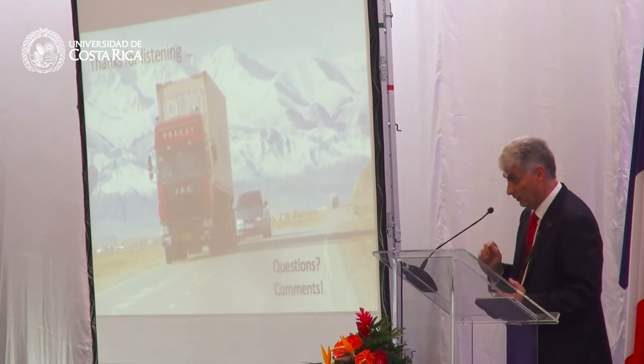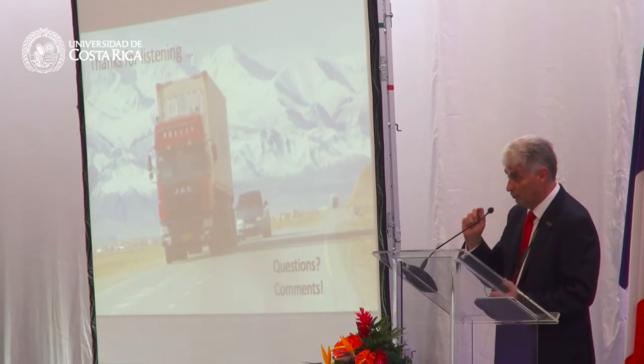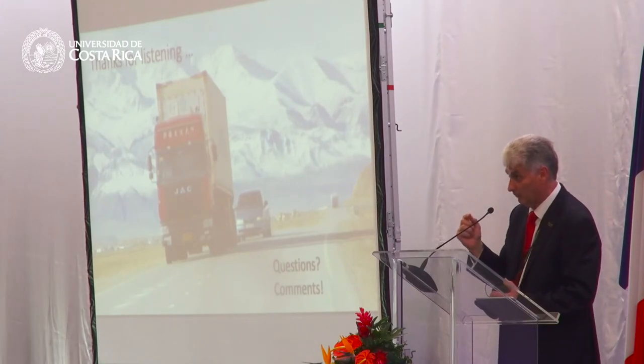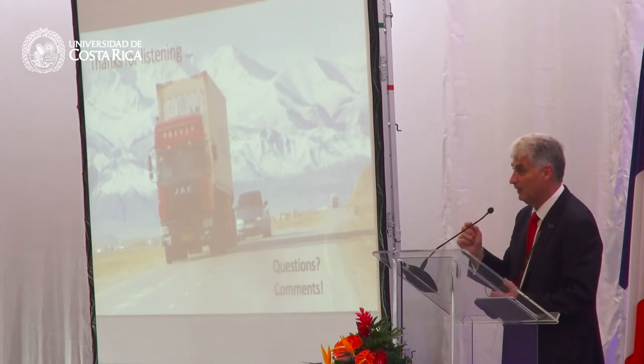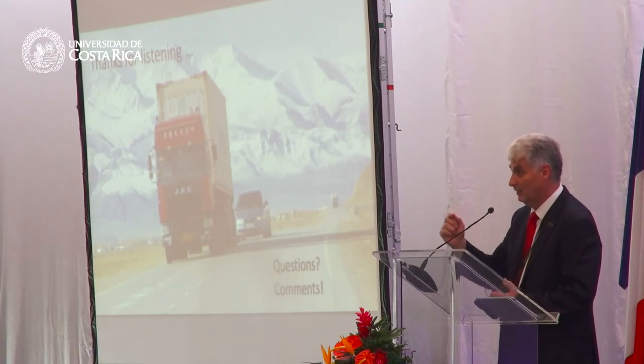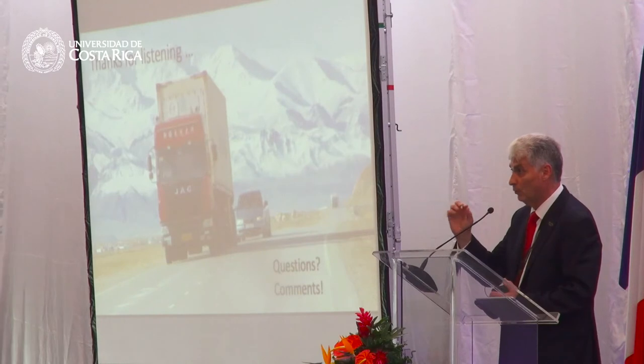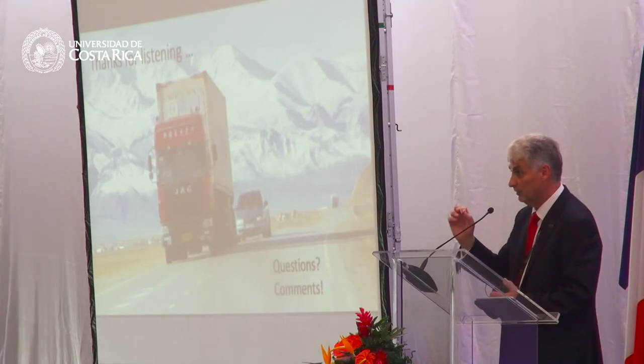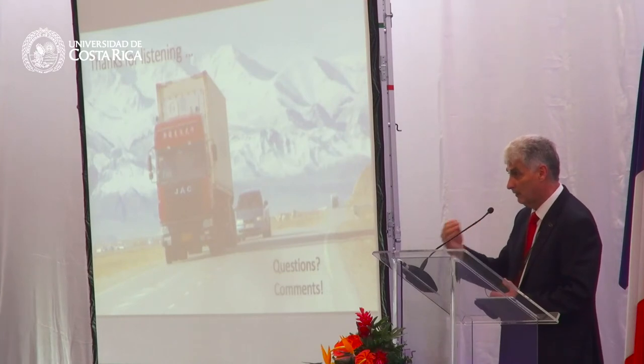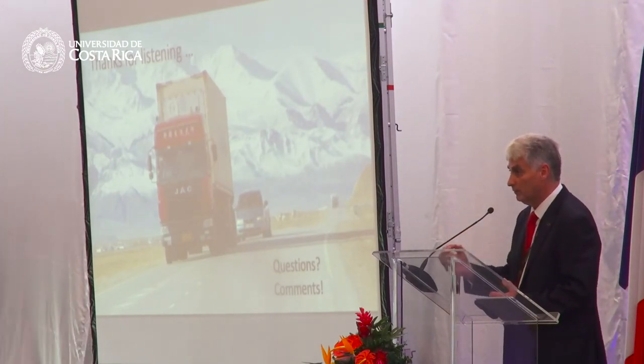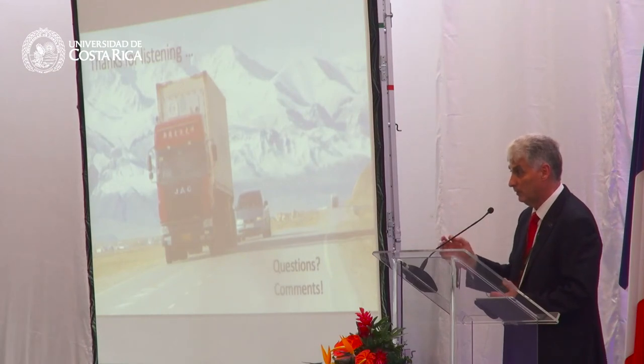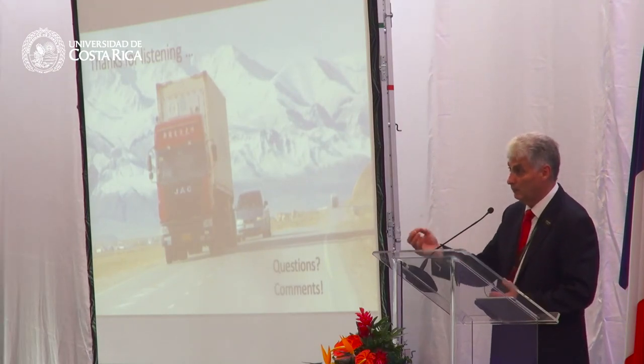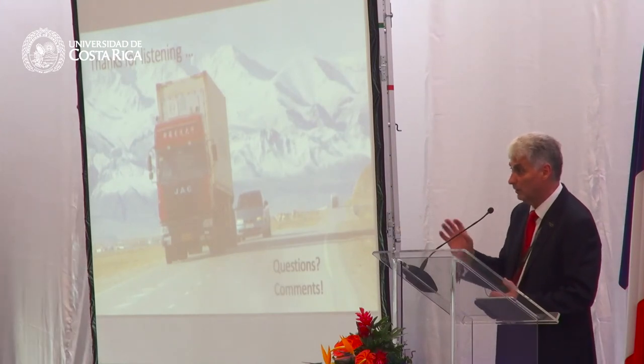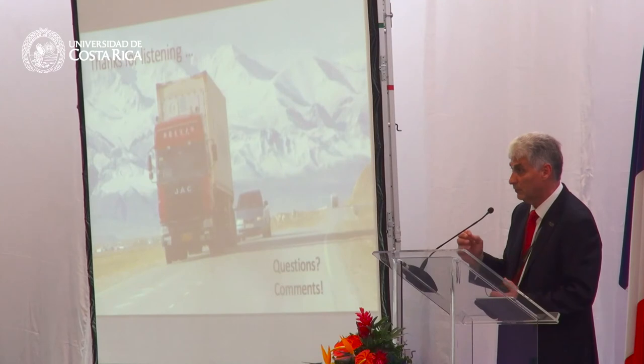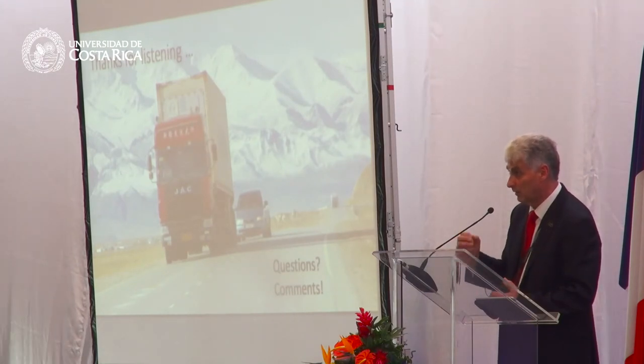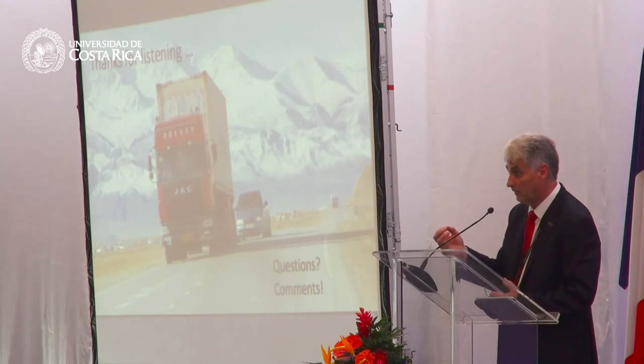The second part of this answer is that if you need to judge the value of a modifier in terms of cracking resistance, we need something in addition to just the linear viscoelastic properties. We also need to know something about its failure characteristics. And for this, we need to have a failure test. In different parts of the world, we see different tests being used. For example, in Europe, I see a test which I quite like, which they have as a cohesion test to classify a failure condition of an asphalt binder.